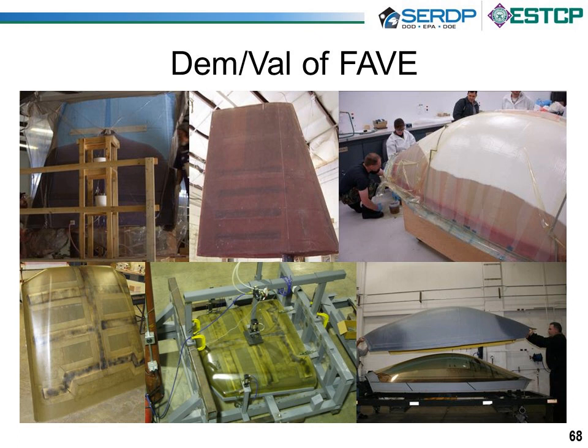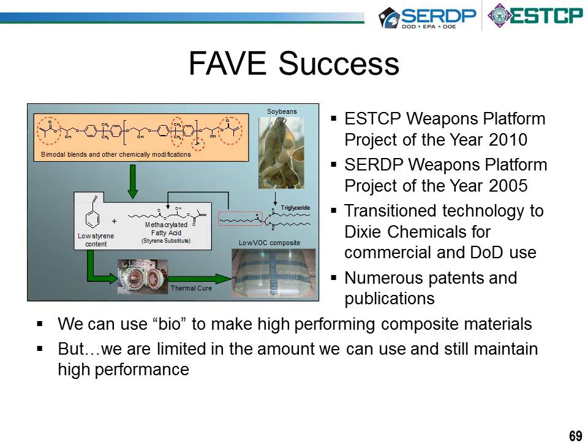And then on the right, we showed the fatty acid vinyl ester resin being used for a particular aircraft part. This is a canopy cover for the F-22, which performed quite well. So moving on, the fatty acid vinyl ester resins were very successful. They won a number of awards. This technology was transitioned to a company, Dixie Chemicals, for commercial and DOD use, but it was limited in the amount of bio content that we can use, and the properties were not fantastic. They were good for low-end DOD applications, but not for high-end.